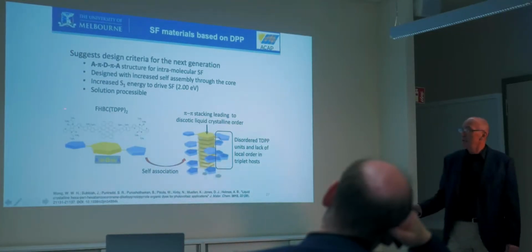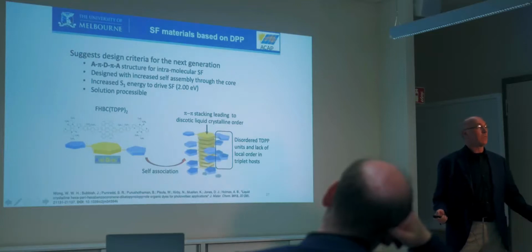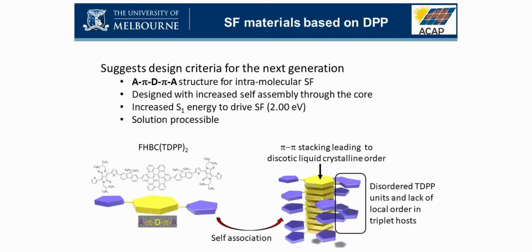We used this material as a donor in organic solar cells, and it wasn't very good, let's face it. But we have this hexabenzocoronene, and that really drives self-assembly. We now have a fluorenyl bridge, but we have the same singlet fission material at the end. And we know that they pack in columns because we'd done all that work, we knew that work, and therefore we basically went back and said, okay, we've got this material, is it a singlet fission active material? And so a little bit more detail, we know it self-assembles, we can see that in solution, we can do NMR, and we can see that these peaks here shift a lot.